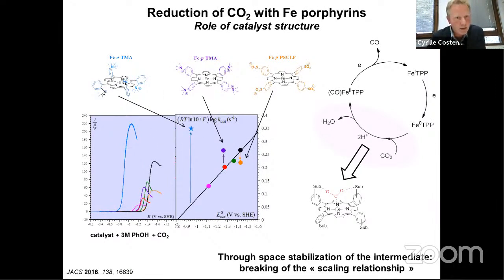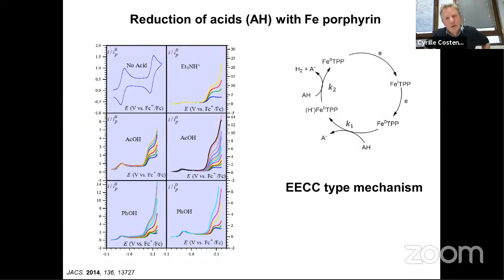By putting those positive charges on the ortho position, we get not only a positive shift of the catalyst through electronic effect, but we have a stabilization of the intermediate that makes the rate constant very, very high, and you get a very efficient catalyst. The same is observed if you put the positive charge on the para position, but it's less efficient. And if you put a negative charge, of course, you have the opposite effect, and so you decrease the efficiency of the catalyst. Okay, so this shows you that you can design better catalysts once you have understood the mechanism.